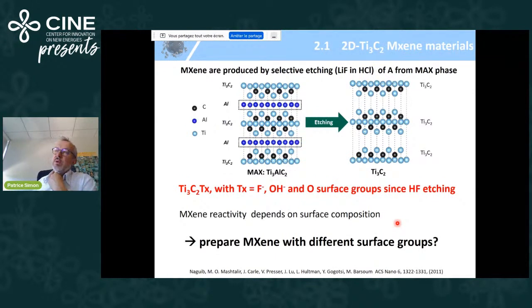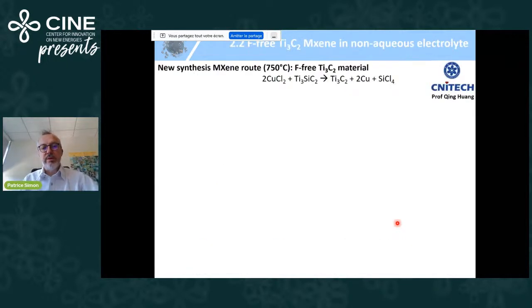The next step and the last example I'm going to show you is the surface of MXenes, which contains surface groups coming from HF or fluorine-based electrolytes needed to etch the aluminum layer. How can we prepare a MXene with different surface groups? Because normally the surface is supposed to drive the electrochemical reactivity. To do that, we designed a new method to prepare MXenes based on molten salt routes.